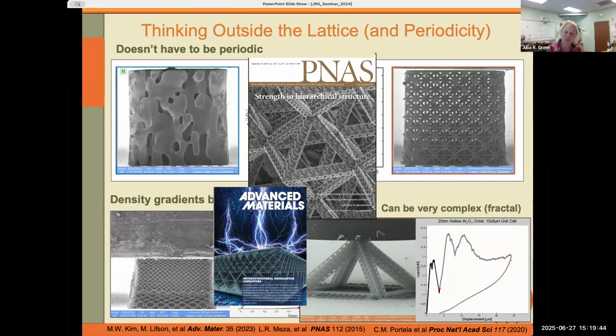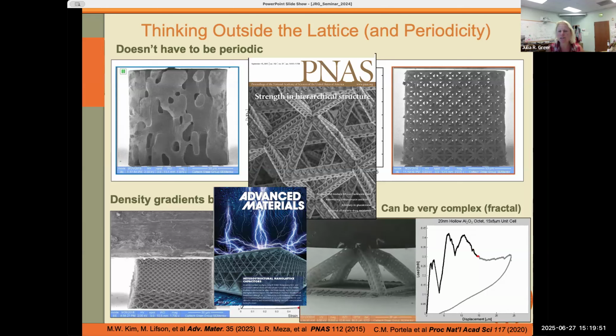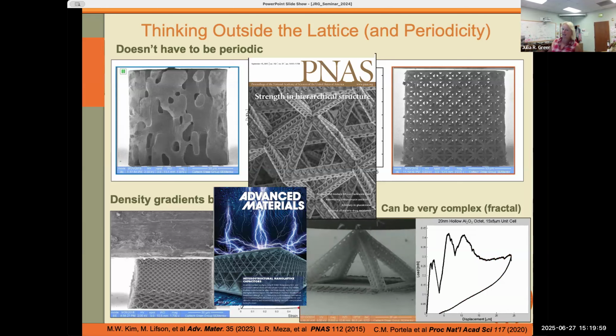This is the deformation of a fractal nanolattice where each beam is now comprised of self-similar unit cells. You can see that it's kinking at the lowest degree of hierarchy, and we're expecting fracture to initiate at exactly that point where the stress concentration is so high. Very unexpectedly, this kind of structure also fully recovers. What that tells us is that this recoverability can be attained under complex stress states and in very complex geometries. So that's what we learned about hollow materials. And this is very important: these are all made of hollow elements.